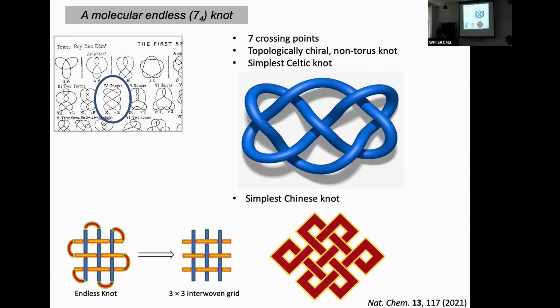And this orientation, where we've got these two nugatory crossings, looks like it has 9 crossings, but it doesn't. It has 7 like this one, because these two crossings are nugatory. That is, they're false crossings. If you just twist here, you can undo them. This gives you a clue about how this can be made from a 3x3 interwoven grid by closing the end groups in this kind of way. That all sounds good, except that 3x3 grids, when we started this work, were unknown in chemistry.